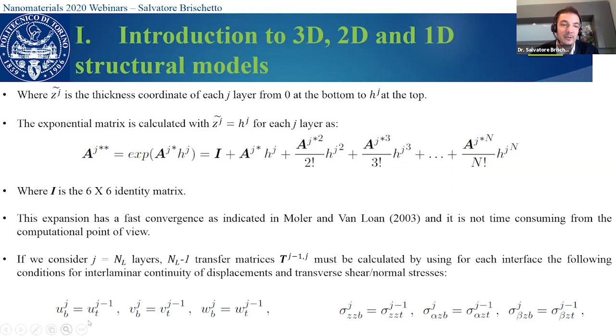We impose these interlaminar conditions in terms of displacement components. This means that each displacement component is continuous at the interface. The bottom value for the J layer is equal to the top value for the J minus 1 layer, and so on. And these are the typical congruency conditions. Then we impose also the equilibrium conditions for the transverse shear and transverse normal stresses. This is the same. The stress component at the bottom of the J layer is equal to the top value for the J minus 1 layer, for the previous layer.